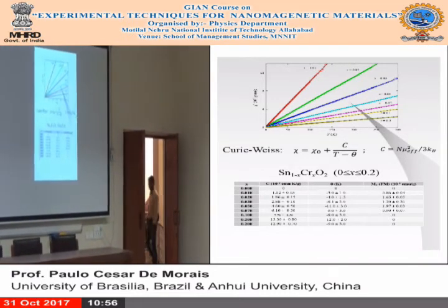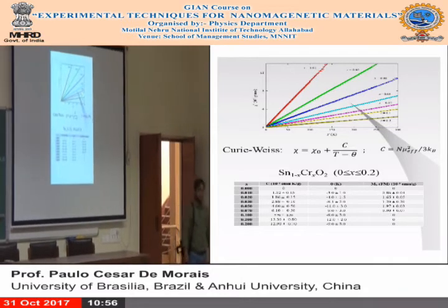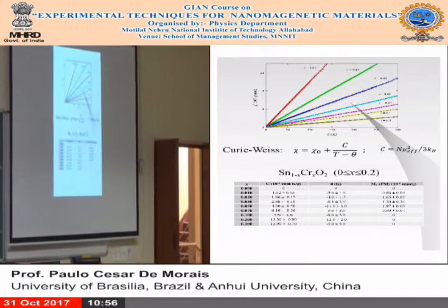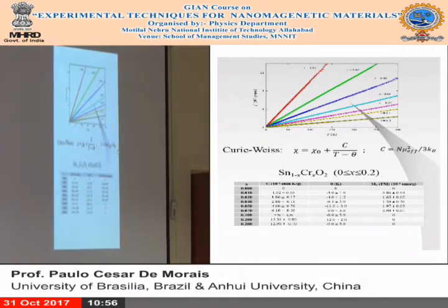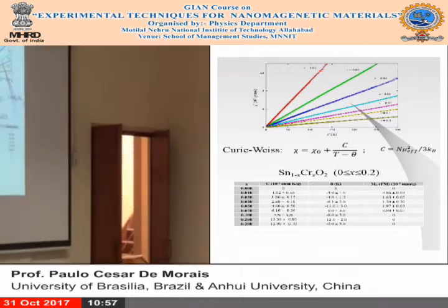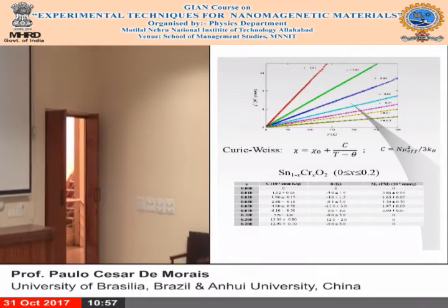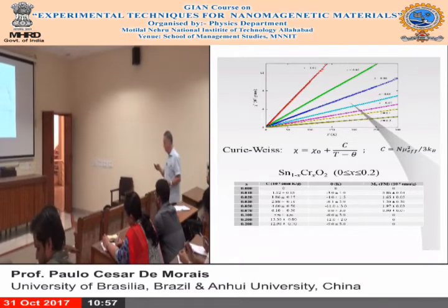So you can see, for instance, you might take the constant you get from the lower doping. You don't expect it to change, right? So that constant is not changing. And then you use the same constant and try to fit the higher concentrated samples. It doesn't fit perfectly. So it is, again, an indication that the system might develop into a core shell, and the shell is a different phase, likely chromium oxide. So that was the end conclusion of this work.